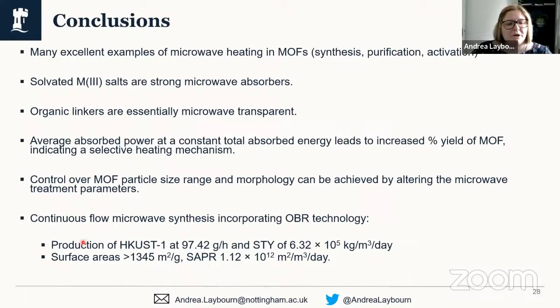And I've also shown you that we move towards continuous flow microwave synthesis to overcome issues with penetration depth, and that incorporating oscillatory baffled reactor technology allows us to produce MOFs at a reasonably high production rate at an astonishingly high space-time yield, and that the surface areas of the materials we were producing were still very, very high.